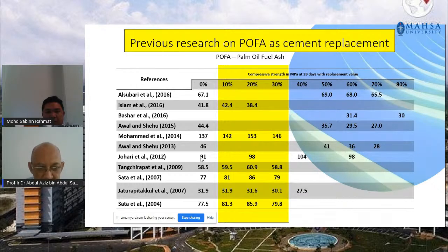And the results, as you can see, when they add 10% to 30% of palm oil fuel ash as cement replacement, are quite reasonable as compared to the concrete with zero POFA. For example, in this case, Muhammad et al. 2014, at 0% POFA, they get a value of 137. At 10%, they got a value of 142, which is much better. At 20%, they get 153, which is even higher. And at 30% of cement replacement, the value reaches up to 146. So it seems to be quite reasonable.